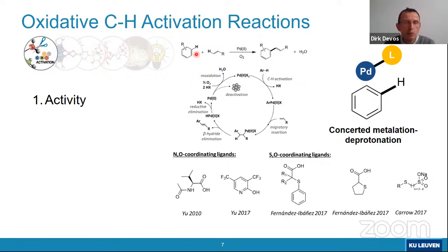Why? Well, because in comparison with, for instance, the activation of a C-Br bond, a C-halogen bond, which is then typically done by oxidative addition on the palladium 0, here you will have to activate the arene CH bond. And that's mostly the more difficult step of the whole reaction sequence. You could imagine, and initially it has been proposed, that this would be an electrophilic reaction of a highly electrophilic palladium attacking an arene, but now there is a more general vision that in many cases you can better explain this as a concerted metallation deprotonation. Metallation meaning that the arene will make a bond with the palladium, but simultaneously you will take away this proton, so it's a deprotonation, and often it's going to be a ligand on the palladium which is going to pick up this proton. This is a concerted process, so the correct name is indeed a concerted metallation deprotonation.